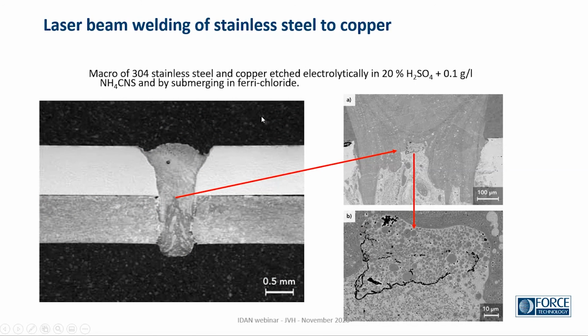Laser beam welding of stainless steel to copper. Again, we can see that we have succeeded in welding, but the properties of the joint are poor. We have cracks in the weld metal, which would probably release a fracture if loaded to a high load.